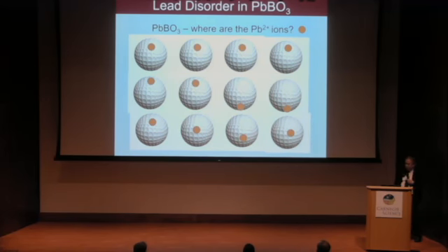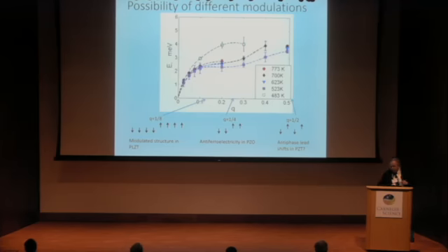I should mention that we do discuss the lead-containing materials, and it is known that in most of the lead-containing perovskites, probably except lead titanate, the lead doesn't want to sit, even above the phase transition, in its special 1/2 1/2 1/2 position. But it wants to be shifted, and these shifts form a kind of spherical layer. Inside this spherical layer, we can have complete disorder, and we can have different types of ordering.